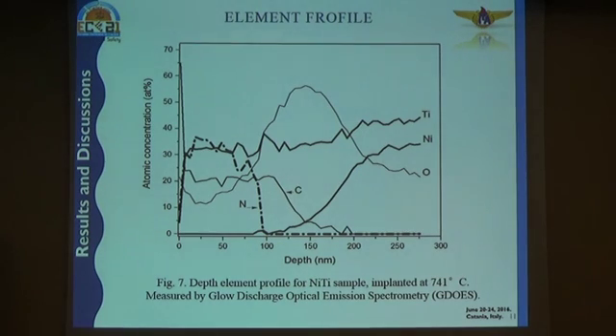As a result, we wanted a Ni-free surface. Here we have an element profile of the wire. In the beginning, at the surface of the wire, we don't have Ni, as we can see in this profile. And when we reach 100 nanometers in depth, the concentration of Ni starts to increase. And what do we have at the surface? We have titanium, carbon, and oxygen, and of course, nitrogen.